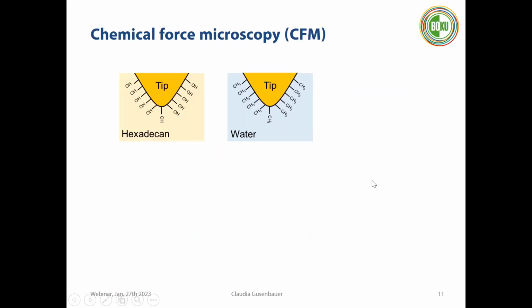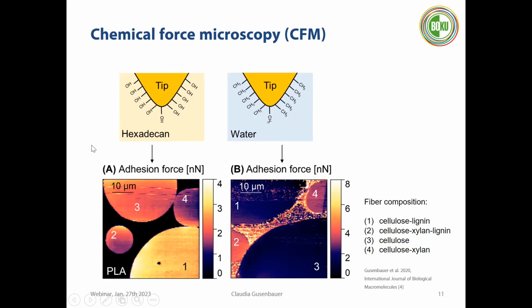And in this method, we do not use standard tips, which are usually made out of silicon nitride. We're using chemically modified tips where we attach certain chemical components which end in a specific functional end group. And then we can set the surrounding to the opposite polarity. For example, we're measuring with a hydrophilic modified tip in a hexadecane environment. And we can also do the same thing by modifying the tip with a hydrophobic functional end group, and then we perform these measurements in water. And then we are again looking at adhesion maps. So how much force we need to move the tip back to the previous position after it touched our sample.